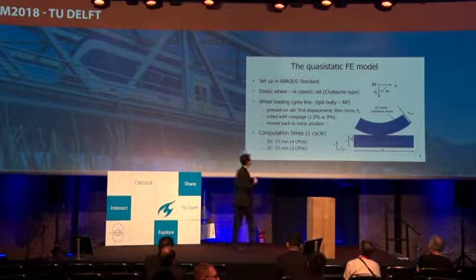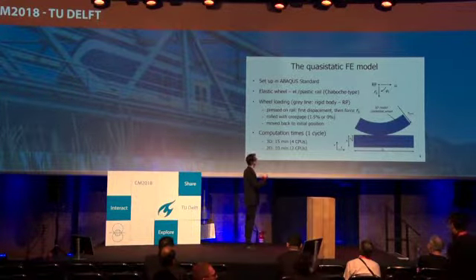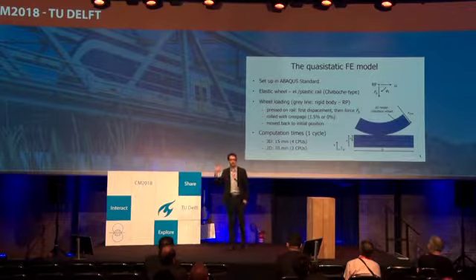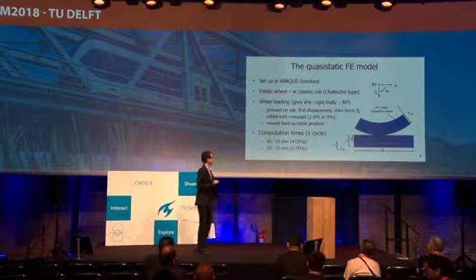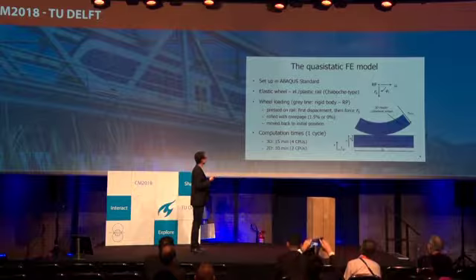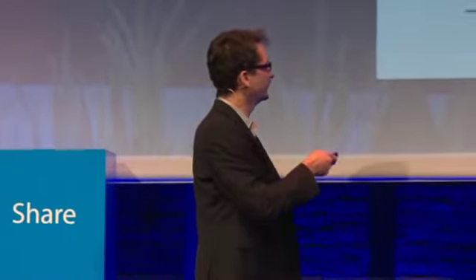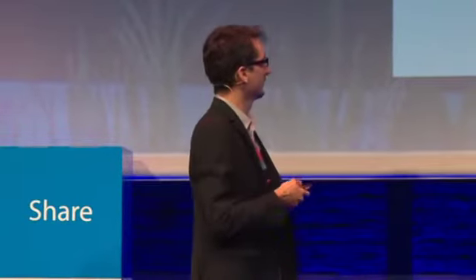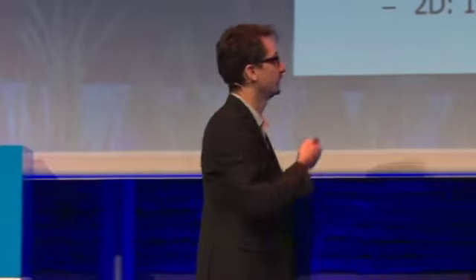The wheel loading goes like that. We have the wheel. Here in the middle there's a rigid part. We press the wheel on the rail, first with displacement, then with the force, with the normal force. Then we roll it with a certain creepage over the rail, and then it's moved back. And then we can cycle that for lots of cycles. Computational times for this model are in 3D 15 minutes and in 2D 10 minutes on some CPUs.